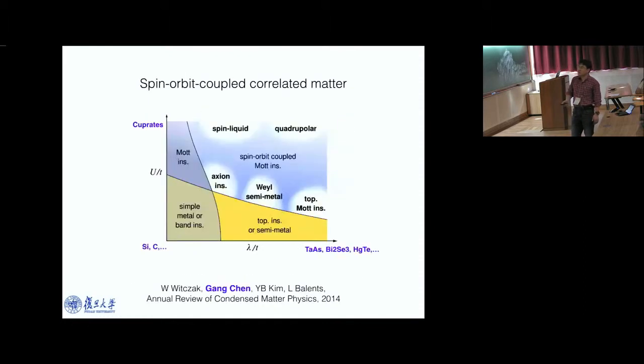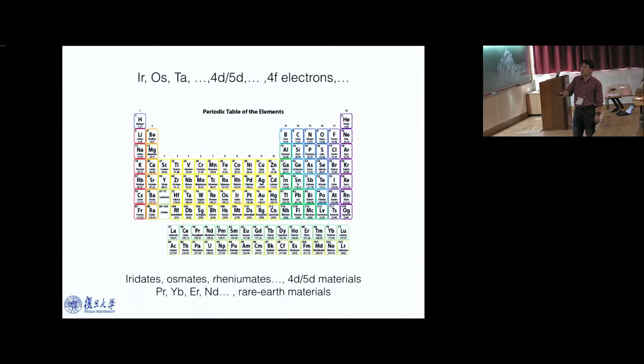This regime is not really just of theoretical interest. There are lots of materials. If you go down the periodic table, the atoms become heavier. Heavier means the spin-orbit coupling becomes strong. For these 5d and 4d electron bands, usually the bandwidth is large. But when spin-orbit coupling enters, it will split these very large bandwidths into multiple subbands, and then each subband has a reduced bandwidth. So effectively, the correlation effect has been enhanced because of the suppressed subband bandwidths.